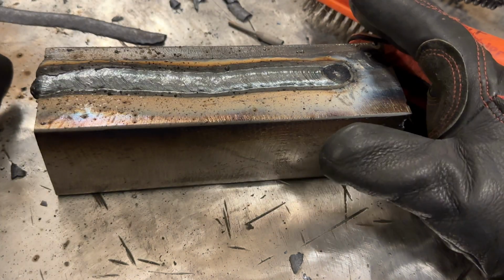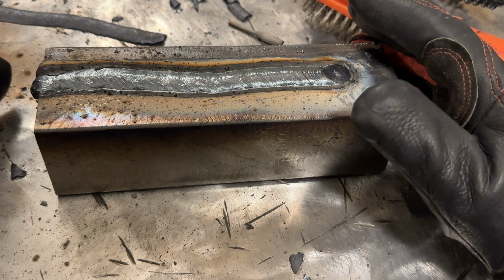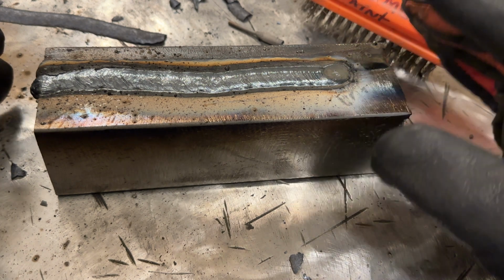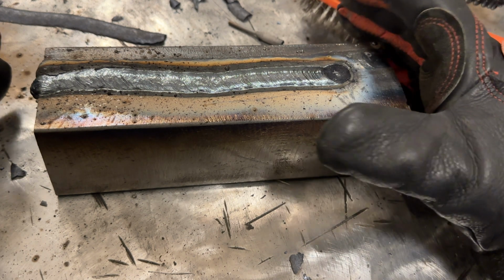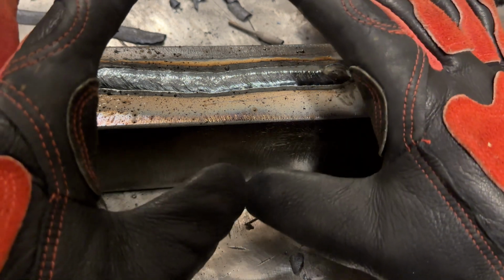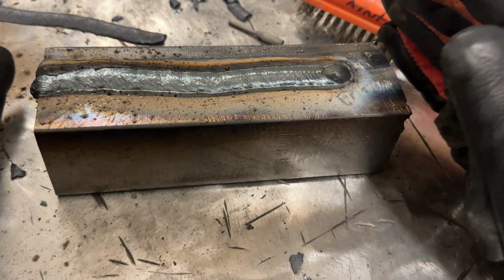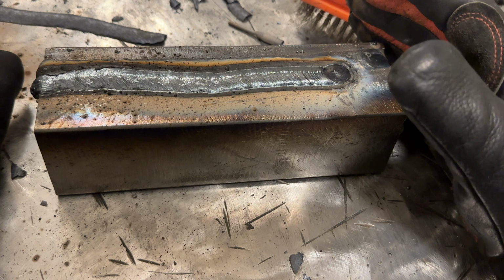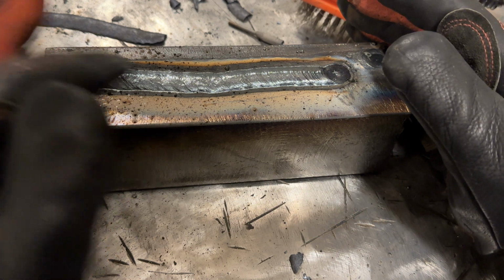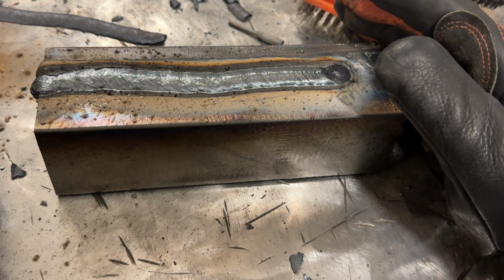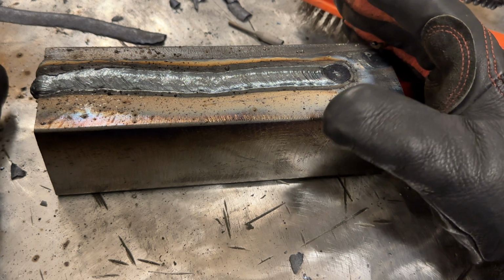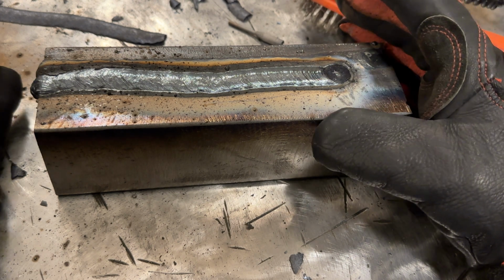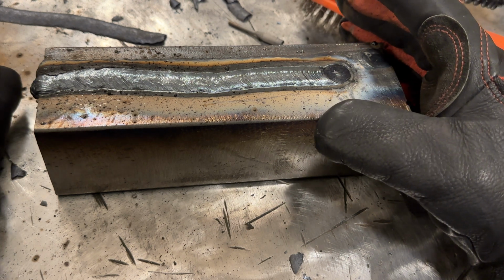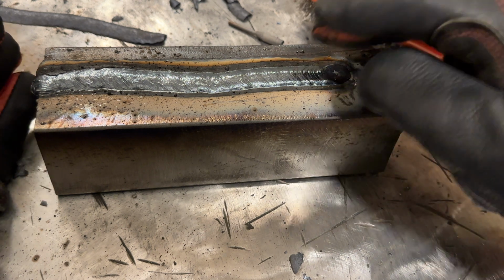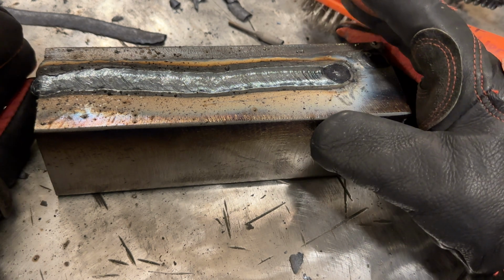As you saw in that arc footage, this is a fairly difficult rod to see the molten puddle on. I mean, there really isn't one per se. Hopefully, you saw it good enough in the arc footage to see that light and dark area. That pretty much differentiates what's liquid and what's not. And even then, it's still somewhat liquid quite a ways back. And that's why you can't run this uphill or overhead. It's so liquidy that you need it to sit on something essentially.